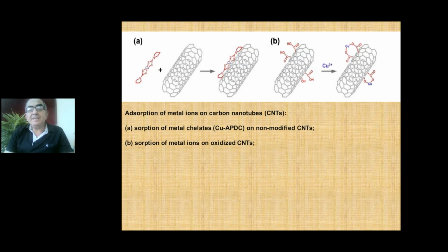For example, in this modification, oxidized carbon nanotubes could be used, and oxidized carbon nanotubes easily absorb copper-2 ions. After absorption we use elution processes, and we can easily separate the copper from the surface of carbon nanotubes by using different eluting solutions.